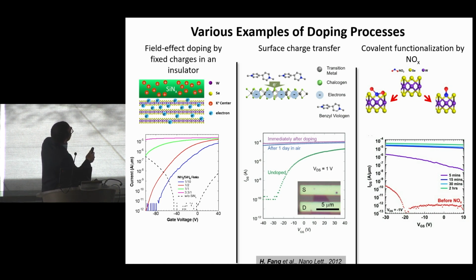So let me show you the different schemes of doping using remote doping. One is to simply put down a nitride layer that has a lot of fixed charges. Nitrides are well established to have fixed charges. You can control the fixed charge density by the plasma conditions. It's a well-established field. And you can control the doping concentration by controlling the fixed charge density.